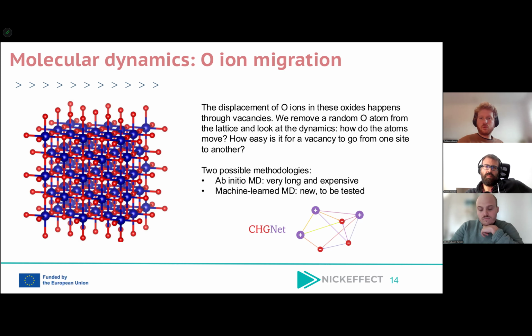And so to do that, we had two different methodologies at our hand. The first one was ab initio molecular dynamics. So this is where the forces on the atoms are computed using density functional theory. So that's quite long and expensive. And so at that time, there was also an alternative methodology that was emerging, and that was using machine learned interatomic potentials to compute the forces that the atoms felt. That was supposed to be much faster, but at the time it was still new, so it needed to be tested. And so here we were using CHGNet.